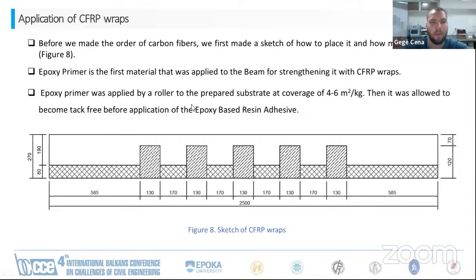Application of carbon fiber reinforced polymer wraps. Before we made the order of carbon fibers, we first made a sketch of how to place it and how much we needed. Epoxy primer is the first material that was applied to the beam for strengthening it with CFRP wraps. Epoxy primer was applied by roller to the prepared substrate at a coverage of 4 to 6 square meters per kilogram. Then it was allowed to become tack-free before application of epoxy-based resin adhesive.